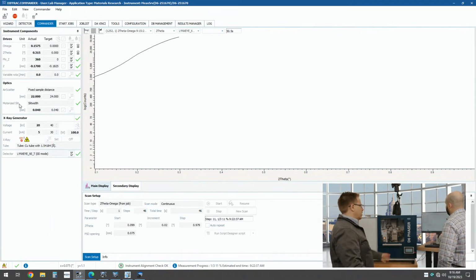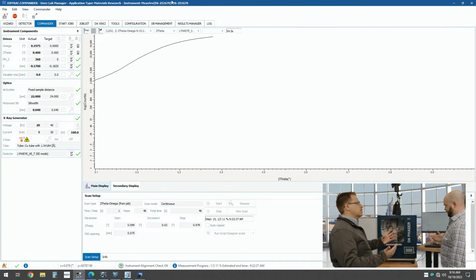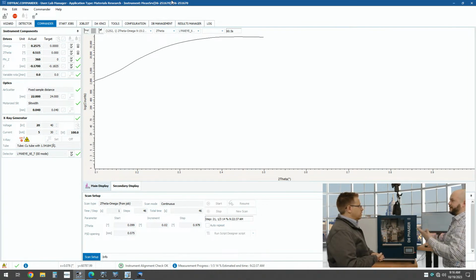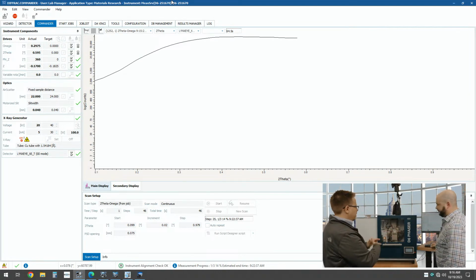All right, so that ability to change the power dynamically with the wizard plus the dynamic range of the detector is suitable for this very, very high dynamic range measurement. That's right. Yeah. Because we're looking at orders of magnitude in intensity, right? And we see that the machine has actually moved all the way down to that XRR geometry.